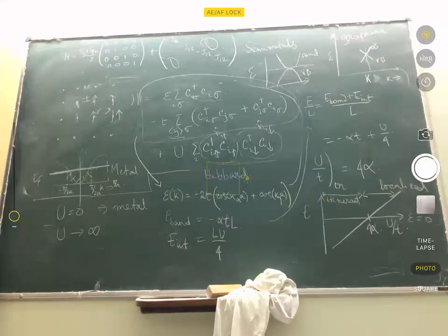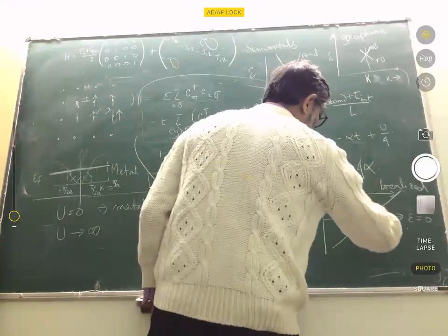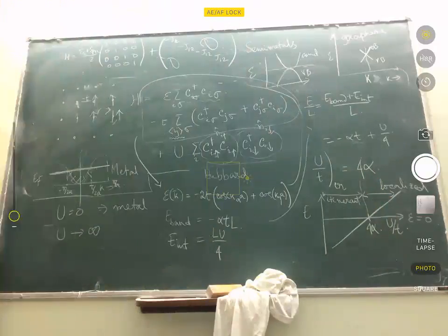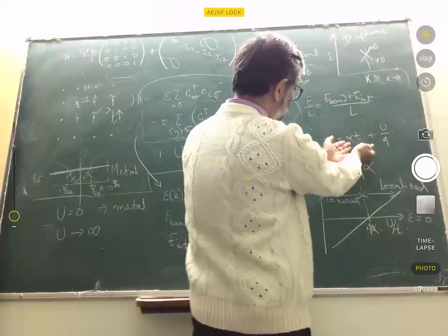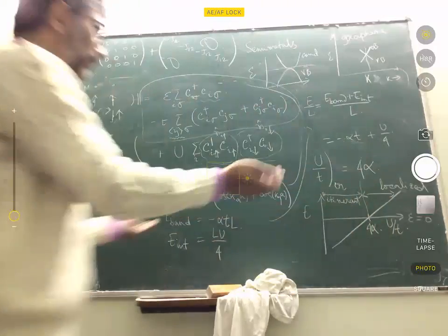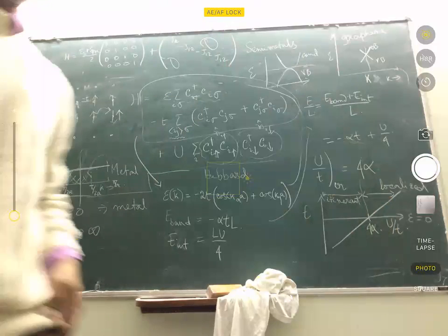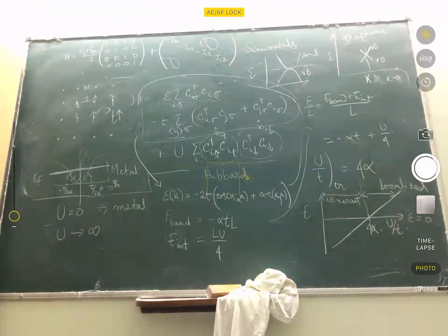So in the left part, the electrons are itinerant, they can move around easily. And then the transition happens at U by t equal to 4 alpha, and beyond which they become localized on individual sites because double occupancy costs energy. It doesn't help before this term dominates, and this term you can view as electrons simply delocalized, that lowers their kinetic energy. Here it lowers their band energy.